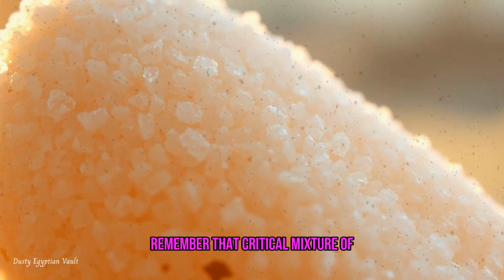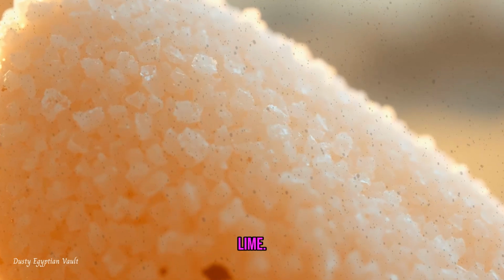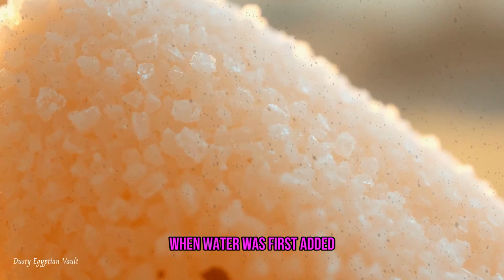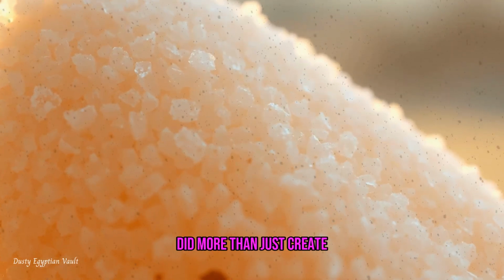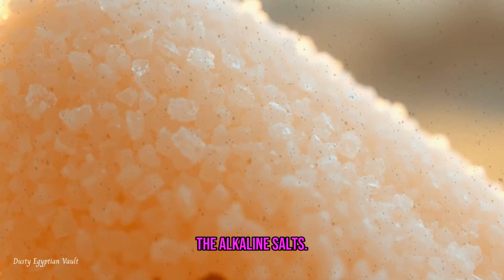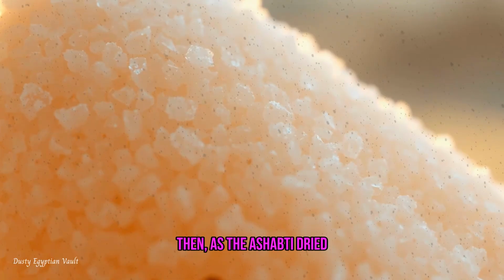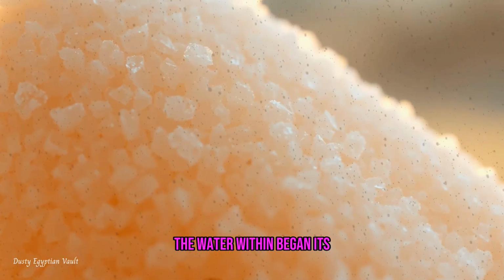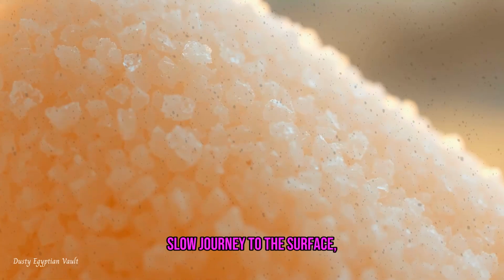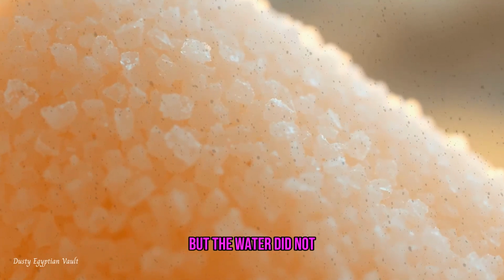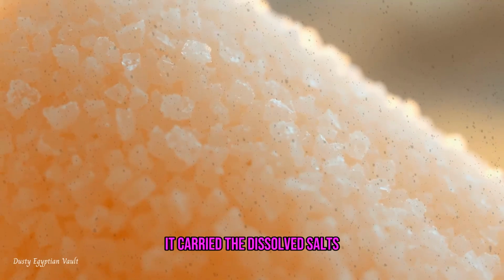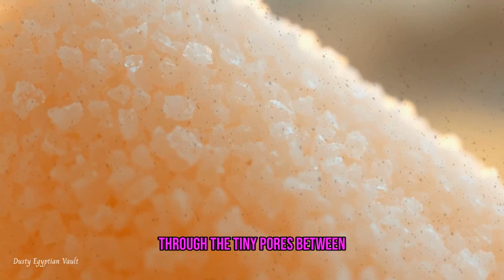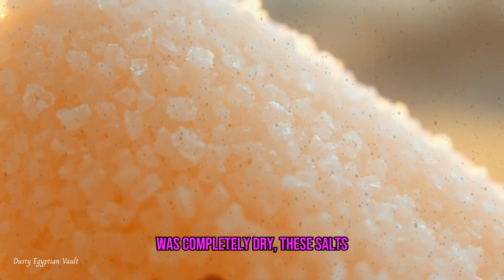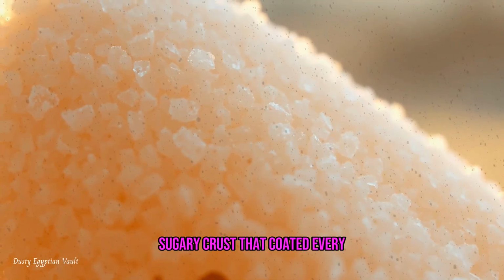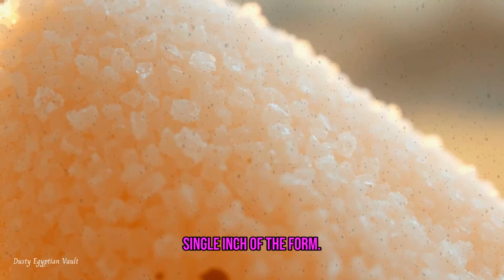Remember that critical mixture of crushed quartz, natron salt, and lime. When water was first added to bind these powders, it did more than just create a workable paste, it dissolved the alkaline salts. Then, as the Ushabti dried over those long, careful days, the water within began its slow journey to the surface, evaporating into the air. But the water did not travel alone. It carried the dissolved salts with it, pulling them upward through the tiny pores between the quartz particles. By the time the figure was completely dry, these salts had crystallized into a fine, sugary crust that coated every single inch of the form.